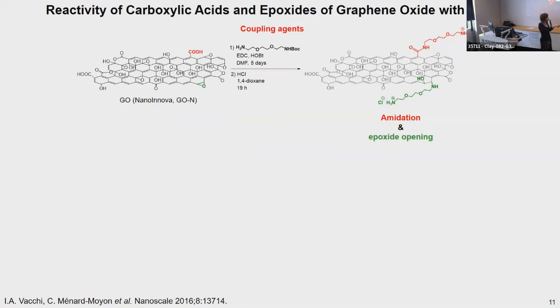So we performed first the amidation reaction, with the concomitant epoxide ring opening, using this diamine derivative with one of the amines protected with the Boc group here. We used EDC and HOBt as coupling agents. The second step was the cleavage of the Boc group to have ammonium functions that we exploited then to assess the level of functionalization using a colorimetric test.